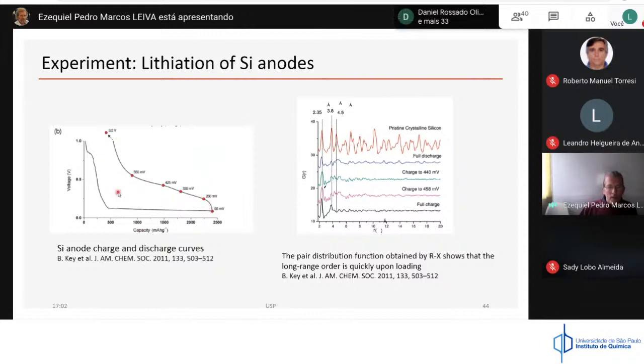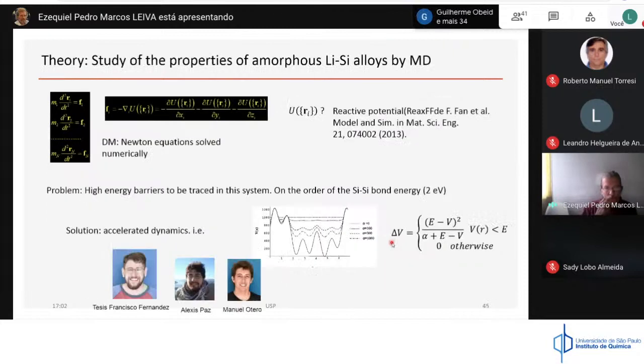One of the things people know is that if you look into X-ray diffraction and you calculate the ordering of the structure, which is reflected in the radial distribution function as a function of the distance, you can see, for instance, in pristine crystalline silicon, a number of peaks that show that your structure is very ordered. But if you charge and discharge your material a number of times, you will see that this very nice structure disappears. That means that your material is becoming amorphous. And so we decided to study this amorphization by molecular dynamics.